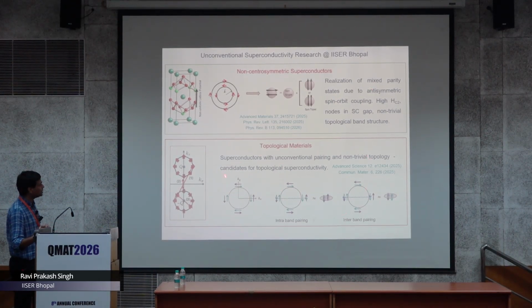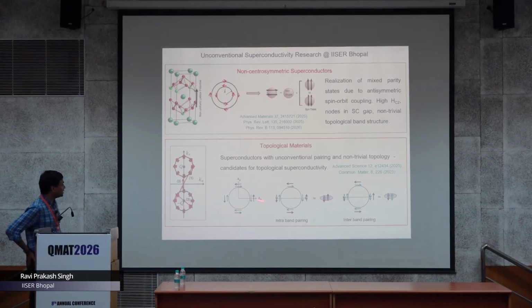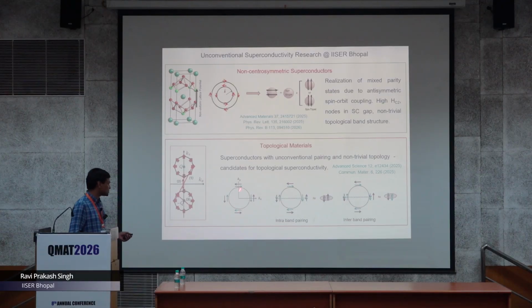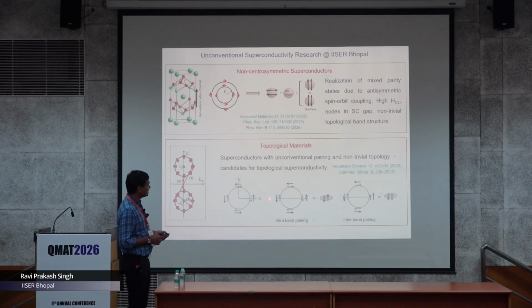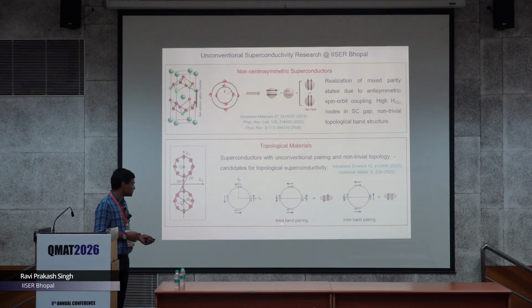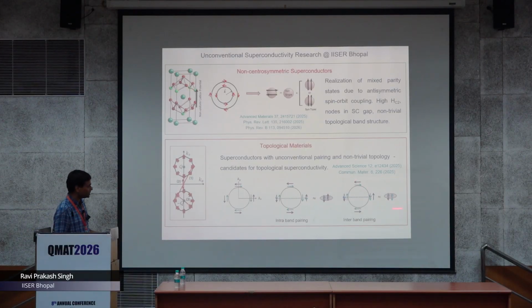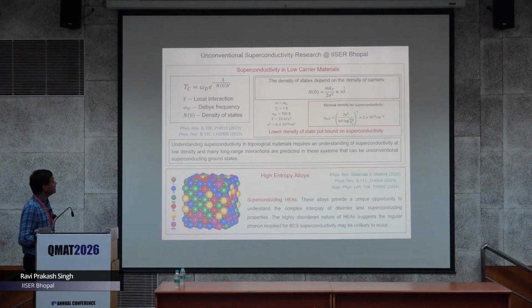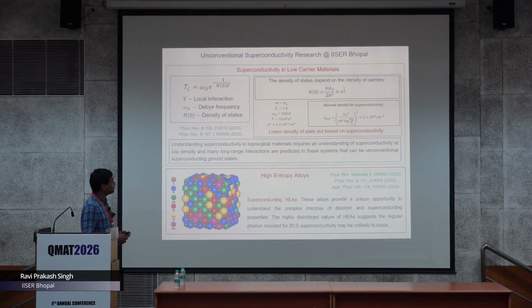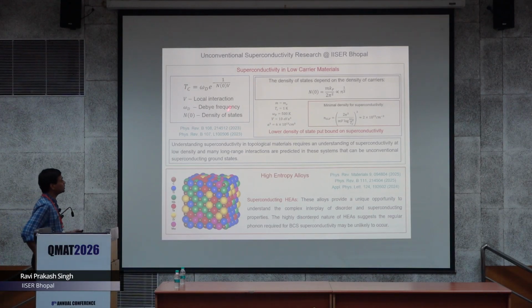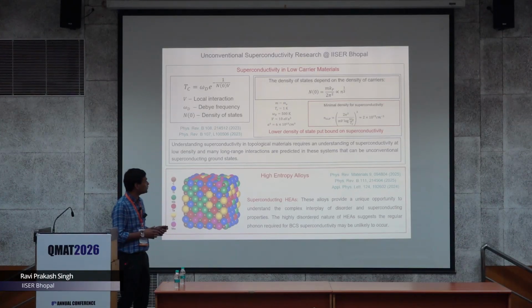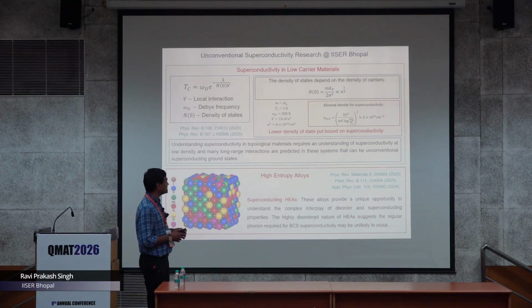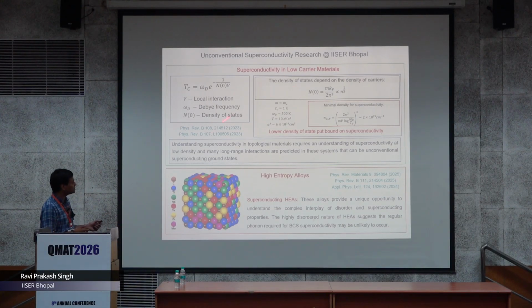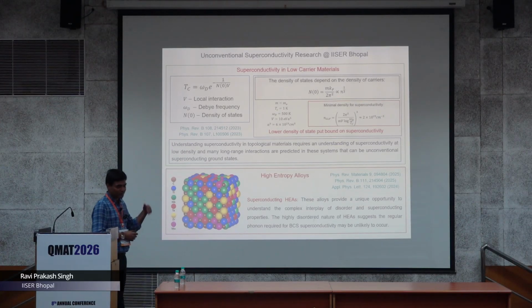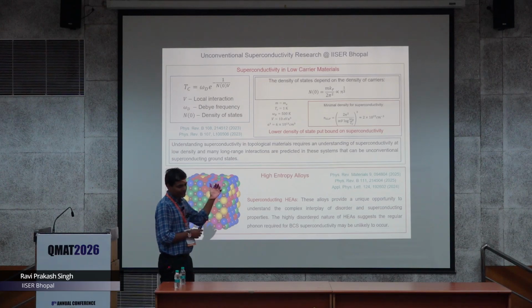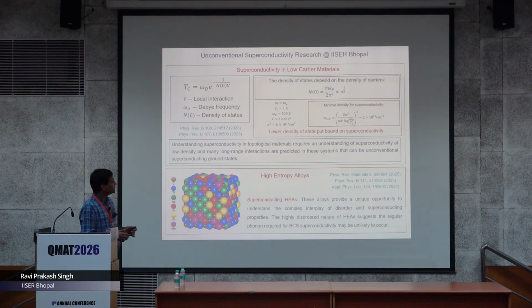The second system we are working on, mostly with Sudeep, is a topological material. Because SOC is very high, it breaks the Fermi surface, so there is a possibility of intraband and interband pairing, and then you can get a triplet superconductor here also. We are also actively looking at superconductivity in low carrier systems, because you need a critical density of states, number density, to form the Cooper pair. If it is not present, then there must be unconventional mechanisms to form it. So we are looking at these low carrier materials, and it is now very relevant for Dirac and Weyl metals, where because of the linear cone, the density of states is very low.